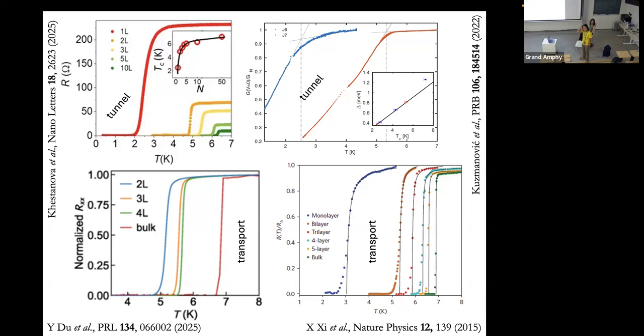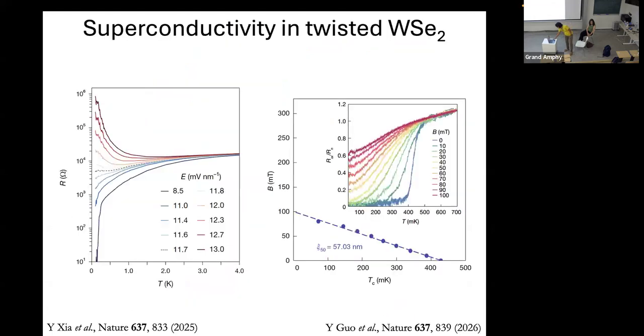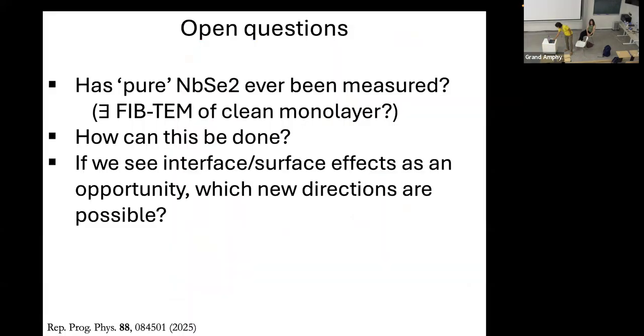Okay, just Shamashi, she wanted to make a comment. Yeah, so I had two comments. Many years ago, like 16, 17 years ago, I struggled for 1 year to contact ultra-thin NbSe2 layers and completely failed. This was before boron nitride encapsulation entered the picture. And there are two notorious problems with NbSe2 which are known. One is rapid oxidation of the surface, and second, loss of selenium atoms. So encapsulation, I can understand, is extremely critical to save the surface.